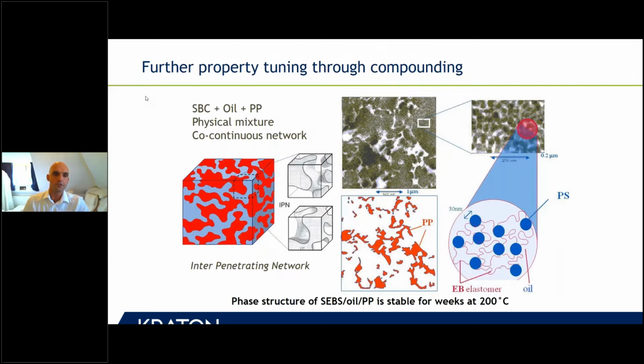Most of the styrenic block polymers are not used as such. It's actually quite rare that people use a pure styrenic block polymer. Typically, they're used in a compound, or as a modifier in a hard plastic, and then you're looking at impact modification. A typical compound would consist of a styrenic block polymer, an oil, and a polypropylene, and you can of course add all kinds of additional components like fillers or even some functional materials. In our company, we always talk about a GOP compound, so it's a Kraton G, oil, polypropylene,